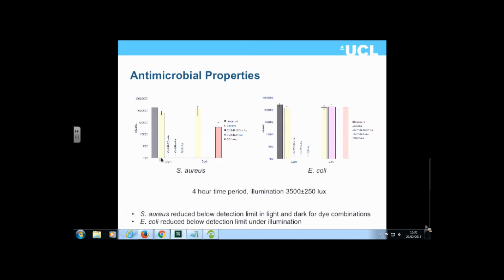This is what happens when we have 4 hours of illumination with a bright light source, about 3,500 lux. But that's not as intense as what you'd get in an operating theatre, where illumination is of the order of 10,000 lux.